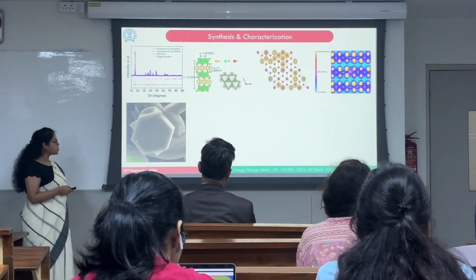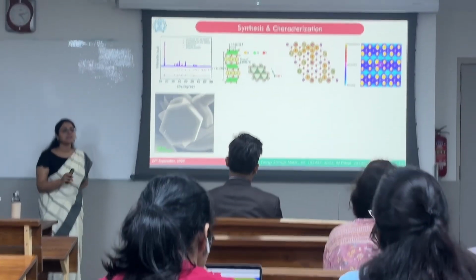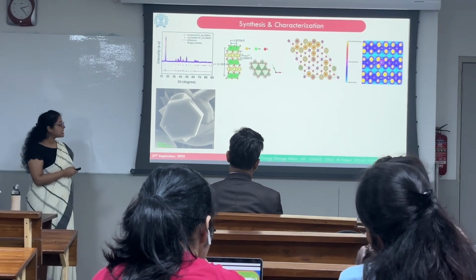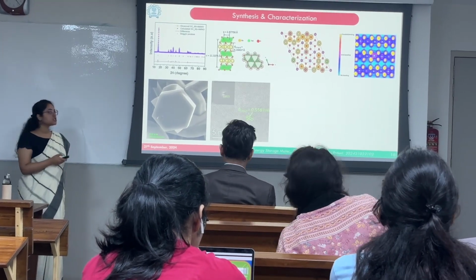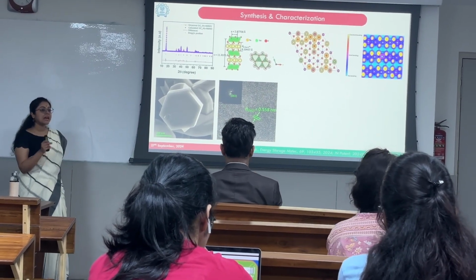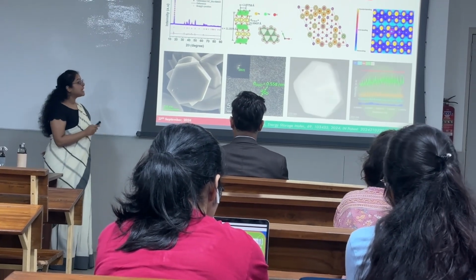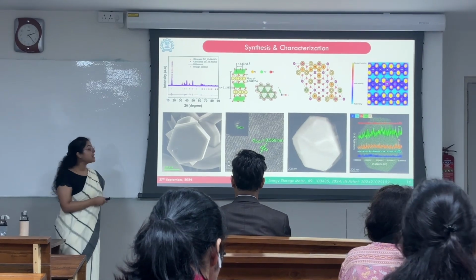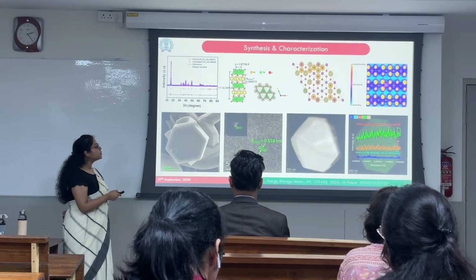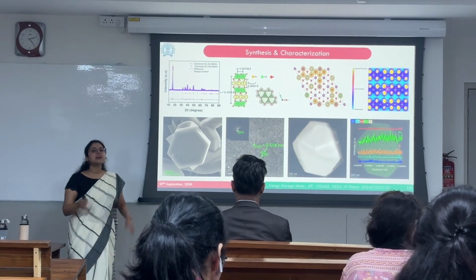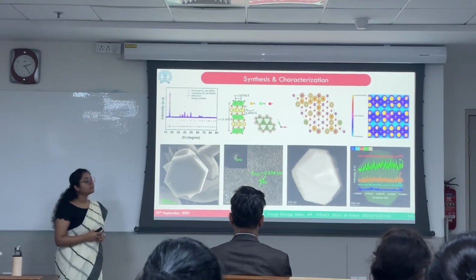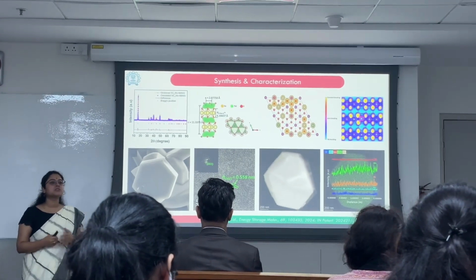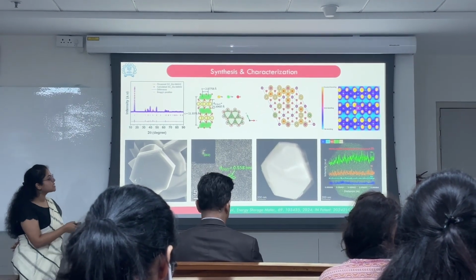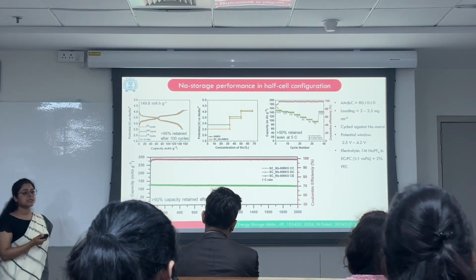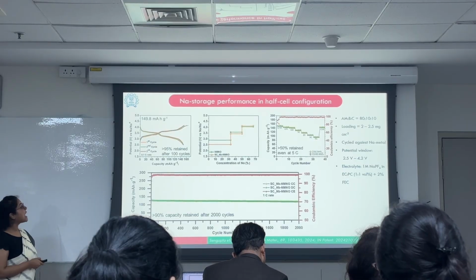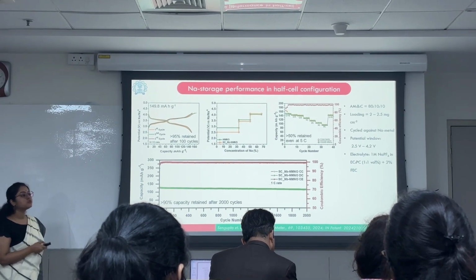Through the scanning electron microscopy, we observed that we could get a clear hexagonal plate-like morphology with clear facets and uniform geometry. And through the high-resolution TEM, we observed that the 002 plane has a d-spacing of 0.558. And through the elemental mapping and line scanning, we observed that in the primary crystals, we could successfully dope niobium throughout the crystal, which is not common, because niobium faces phase segregation and atomic surface rearrangement problems. So this is the first thing we obtained. Then we tested the electrochemical performance against the sodium metal and cycled it within the potential window of 2.5 to 4.2 volts.